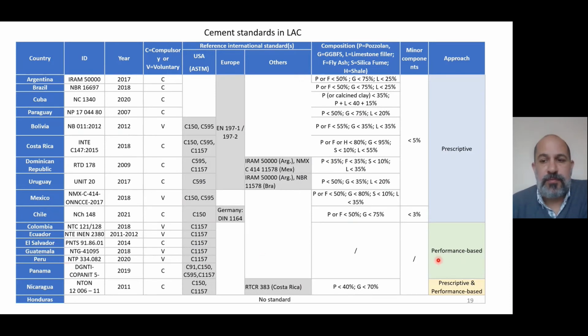But these two approaches do not correlate completely with the clinker factor we have in the different countries. So if we take, for example, the case of Peru, I was mentioning earlier that Peru has the highest clinker factor, but still a performance-based approach. So it seems that there are other limitations to the clinker factor than the regulation itself.